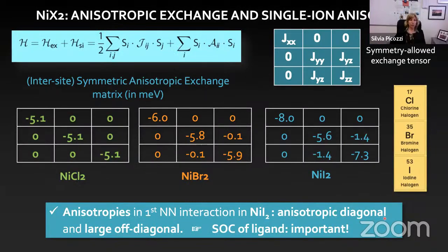Okay, so now we estimated this and we did it for the series, right? We started from nickel chloride, then moved to nickel bromide and then to nickel iodide. What we get from nickel chloride is minus 5.1, minus 5.1, minus 5.1 elsewhere, which means that nickel chloride is a pure Heisenberg system. If I increase the spin-orbit coupling a bit, then I start seeing some effects. The three diagonal terms get different and also some off-diagonal ones appear. And in nickel iodide, this effect is even larger, much larger.